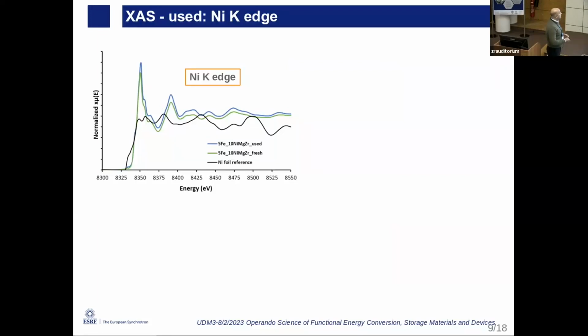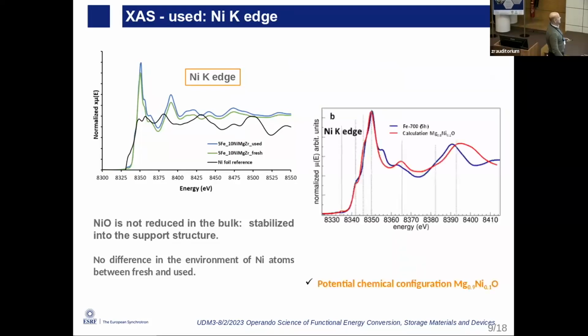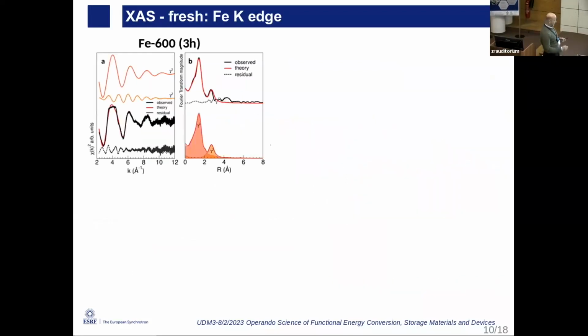Interestingly, we also want to study the used material, because we want to understand what is happening in the end. We don't see any variation at the nickel edge, and basically we can confirm the same structure of the nickel. So now we move on to the iron edge, and for the iron edge we are interested in the difference with temperature. We see that when we deposit the oxide on the magnesium support, the nickel-modified support, clearly we have an iron oxide. Basically, we can see two shells.